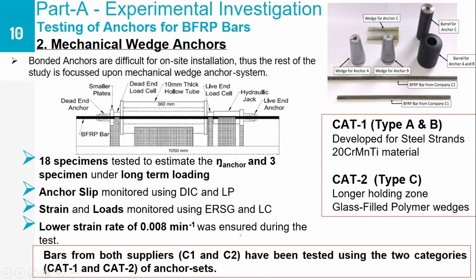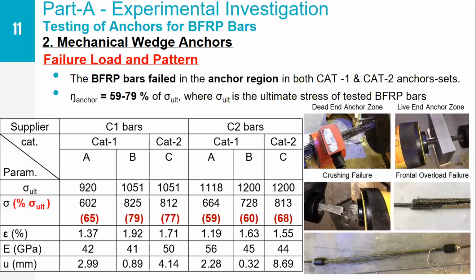So now let us look at the test results that we got. What we noticed is the BFRP bars primarily failed in the anchor region for both the category 1 and category 2 anchors. And two types of failure were observed. One is the crushing failure, which is basically caused inside the anchor region due to the crushing of the BFRP bars by the serrated wedges of the anchors. And the other one is the frontal overload failure, which is due to the rupture failure in the vicinity of the anchor outside the barrel. So this type of failure has also been observed primarily at the live end of the BFRP bars.